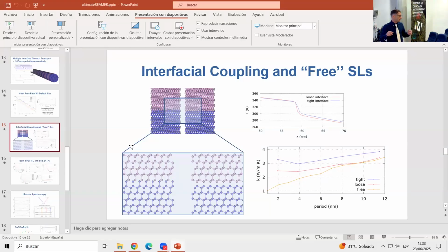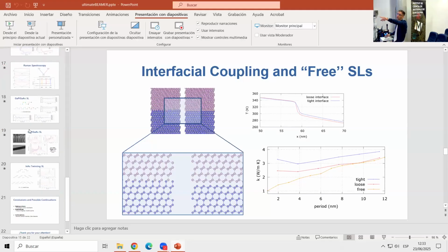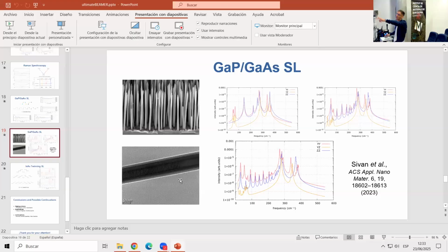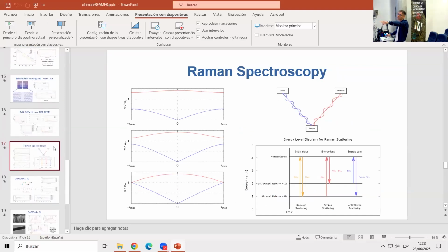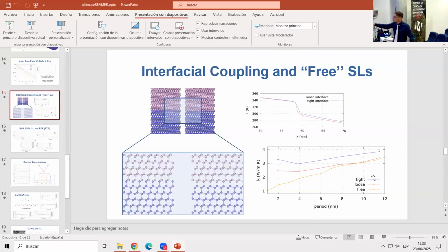But even here, if I'm not wrong, people have grown some perfectly flat interfaces, literally atomically flat interfaces. I'm sure that you don't have that kind of control over the interface kind and over the possible alternation of different interfaces when you grow superlattices of this size. Here, everything is way less precise and way more random. So here you still observe coherence, and according to what you observe in the experiments, somehow you would say that you should still observe coherence in the last line, in the yellow one,